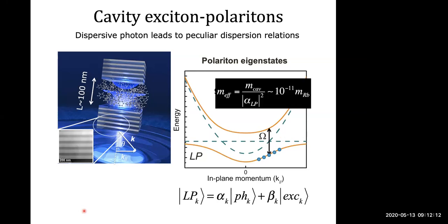Another interesting feature is the fact that this lower polariton branch has a very small effective mass, which is on the order of about 10 to the minus 11 times the mass of a rubidium atom. And this low effective mass is really the feature which garnered quite a bit of attention at the beginning of this field, because it puts forward the prospect of achieving Bose-Einstein condensation of polaritons at an elevated temperature.